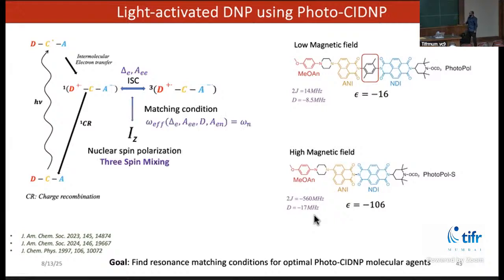We did not have our setups ready then, so we thought of understanding how it is working. What we understand so far is, when these molecules are optically excited, they go into an excited singlet state, and can do intersystem crossing to a triplet state. There could be different ways of intersystem crossing, and one of the ways involves nuclear spin. If there is a nuclear spin nearby these spin-correlated radical pairs, then depending on the parameters, the nuclear spin can be hyperpolarized through a 3-spin mixing mechanism.